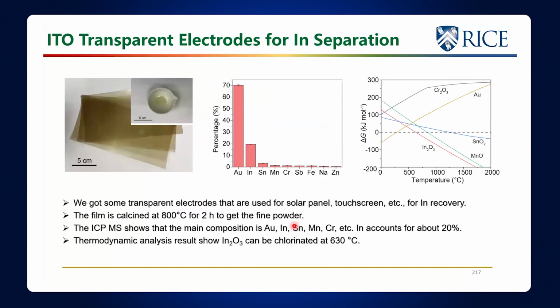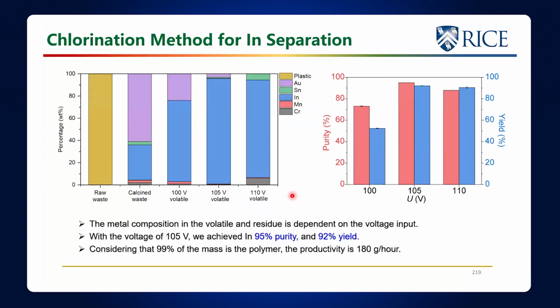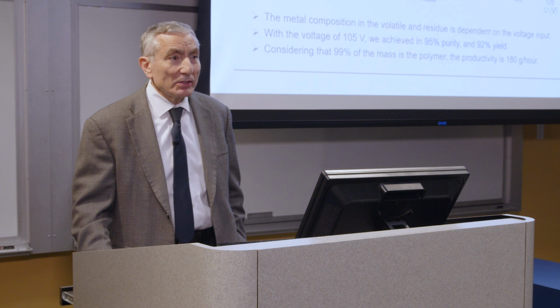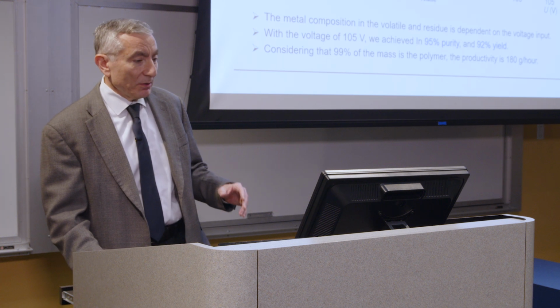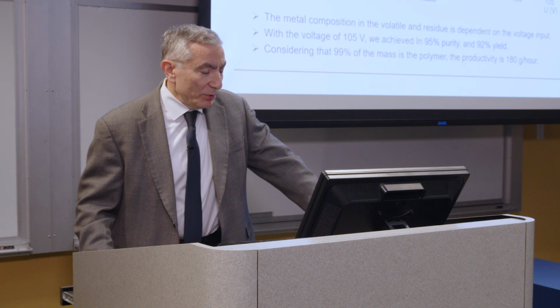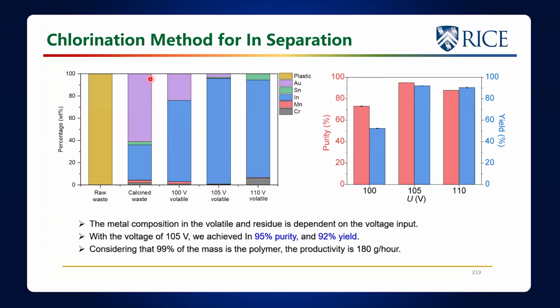But if we go back to the original chart here, the amount of chromium is actually very low. What you can see here is the raw waste is mostly plastic. The metals are just a small amount relative to the plastic, and that's the way the industry wants it. The metals are much more expensive than the plastic. Then you calcine it, which means you heat it up in air, so the plastic's all gone, so it's mostly gold. Then you have some tin, and there's the indium. Then if we do the flashing at 100 volts, you get this much higher amount of indium.